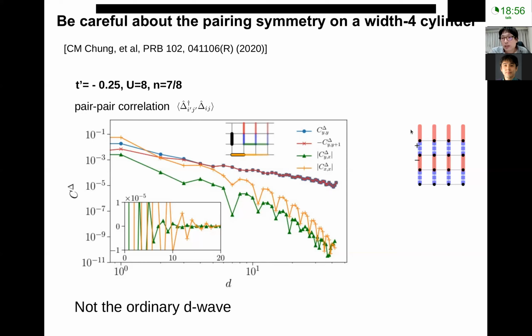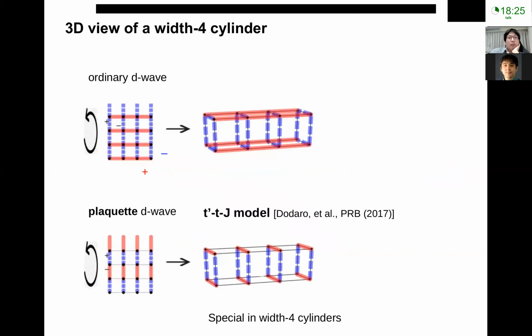So it's more like this: you have different signs alternating in the vertical direction. The correlation to the horizontal bond is basically exponential decay, showing there's very weak correlation to the horizontal bond. So this kind of new pairing symmetry is not as we would expect.